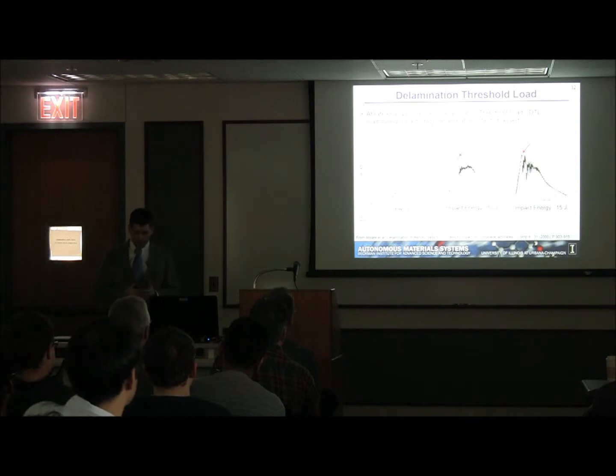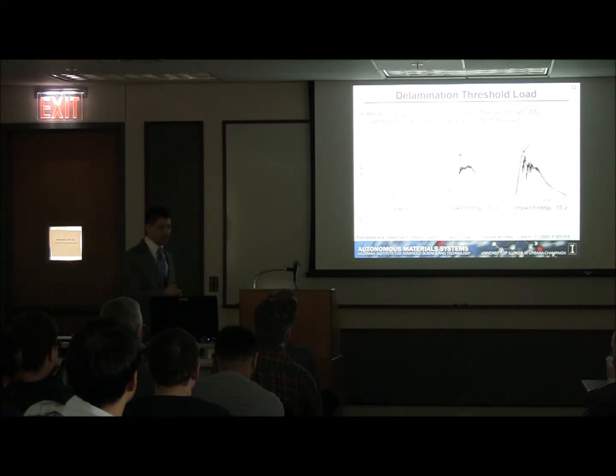So interestingly, when going through the literature, we can see that other authors have identified this drop in the load during impact and have actually coined it the delamination threshold load. So the load required to introduce delamination damage inside the specimen. So this is from another author's work where he's identified this first reduction in load as the delamination threshold load. And again, this corresponds roughly with what we see in our specimens.